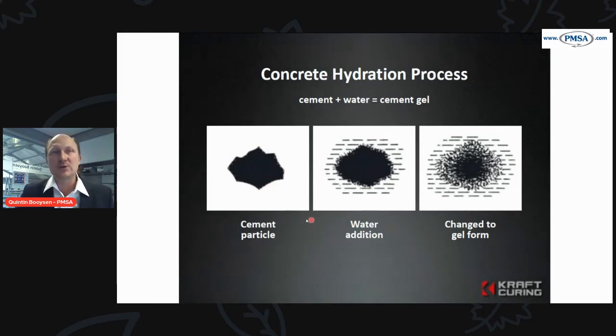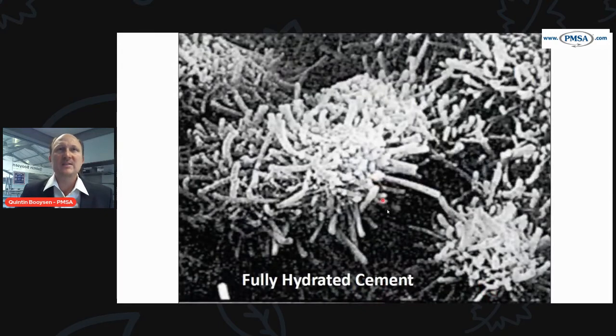We then add water, which is in the concrete process, and the water gets into the structure, and chemically it starts changing from a solid into a gel formation. And that gel is critical because the gel is what ultimately becomes part of the matrix, the glue within the structure of concrete. This is zoomed in several times; you can imagine it went from 45 microns to something that's about 10, 15 centimeters.